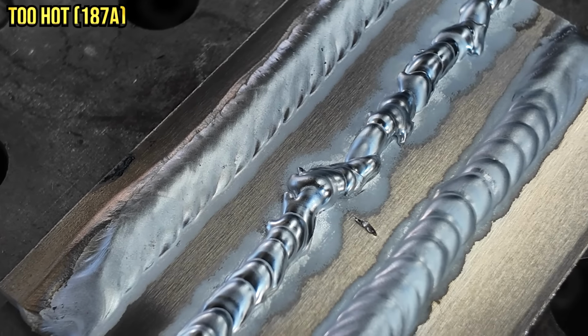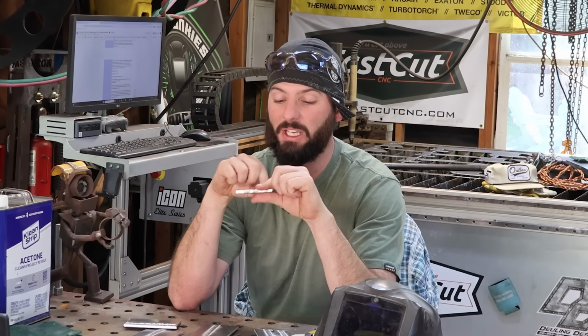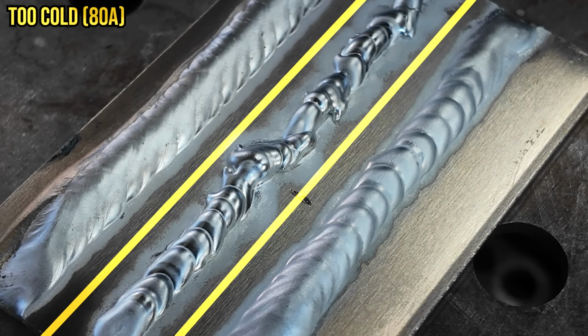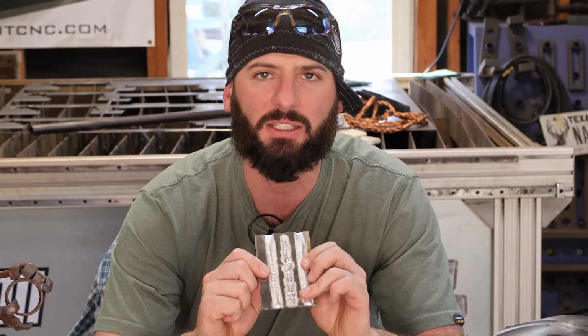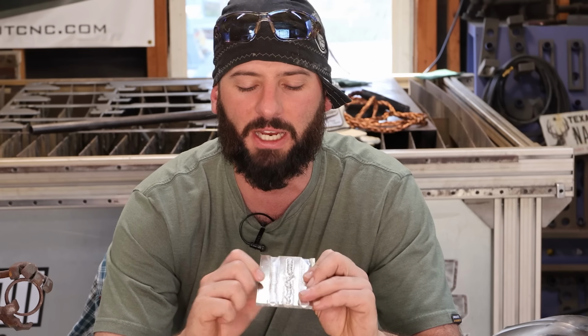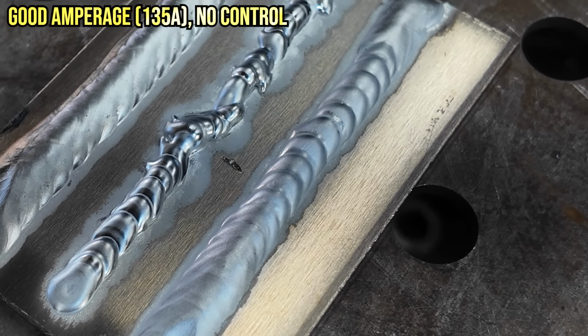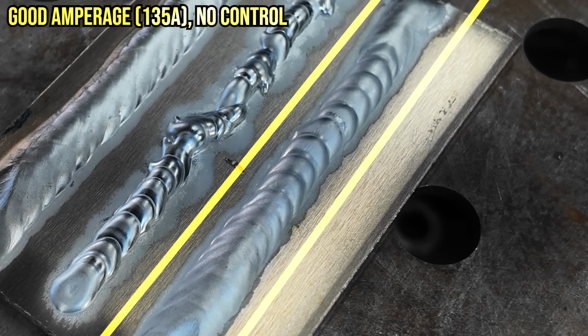And you can even see on the backside that we've got a little bit more penetration than, say, this middle weld, which is far too cold. It's lumpy, it's humpy. It is the shiniest of all of them. We got a lot less amperage here, but still none of that shiny. We're just not controlling our variables well enough. We still don't have that balance.